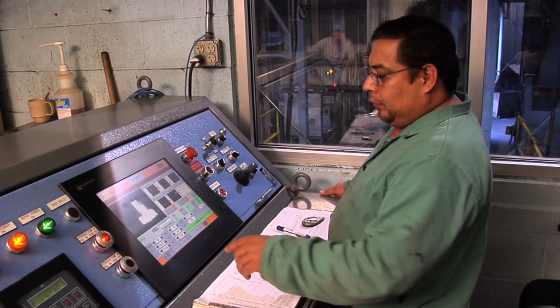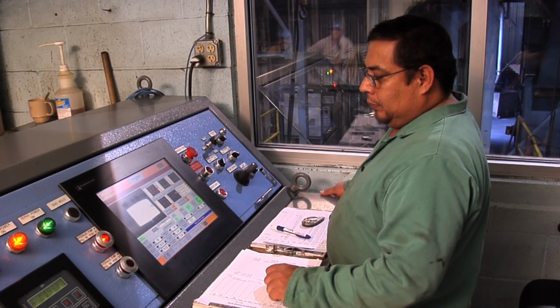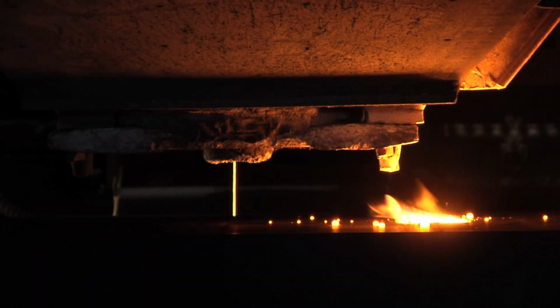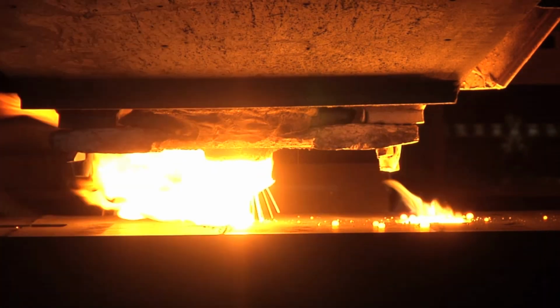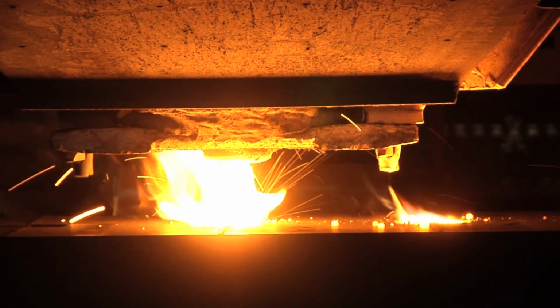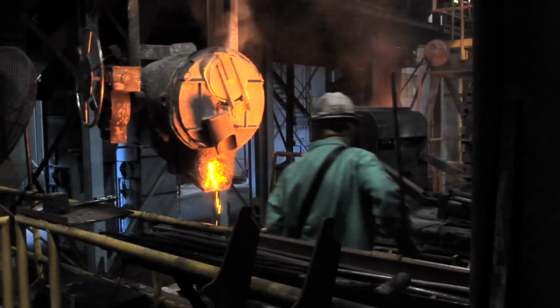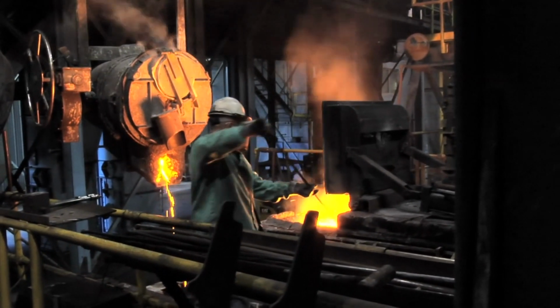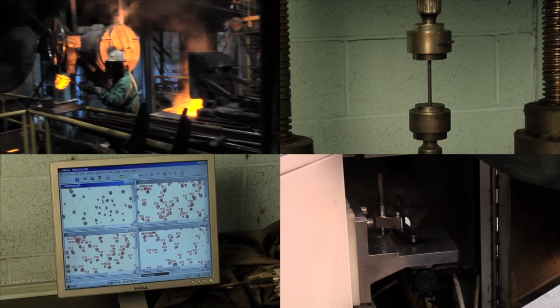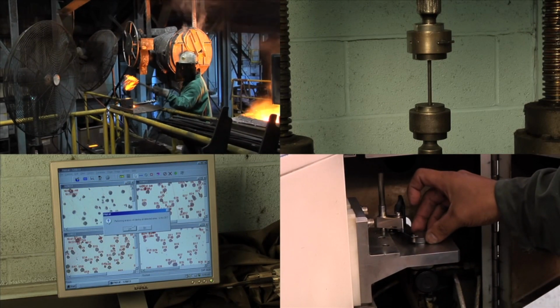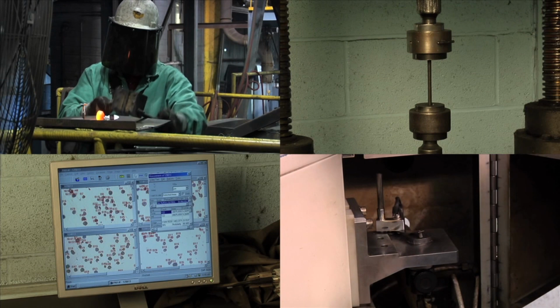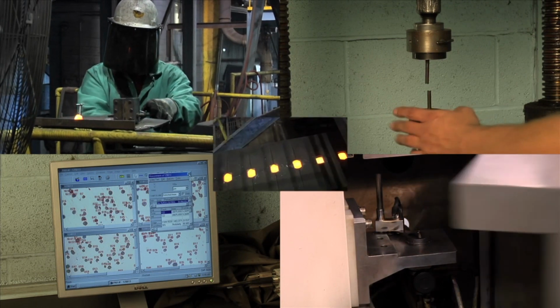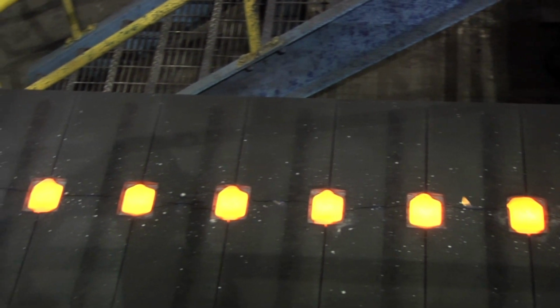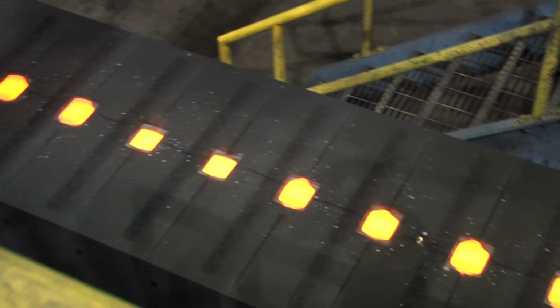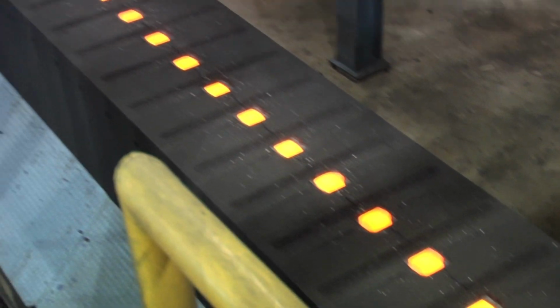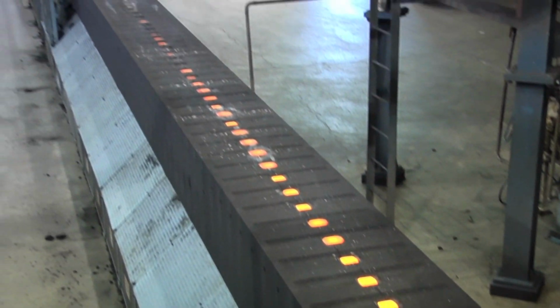Each sand mold block now passes through the pouring machine, where it is automatically filled with a precise amount of liquid ductile iron, heated to temperatures of over 2,600 degrees Fahrenheit. A sample of the treated ductile iron is taken, and its properties are assured. In all, a total of 4 quality assurance checks are eventually performed throughout the process to assure the physical properties of the iron. Once the pouring process is completed, the sand molds continue traveling along the conveyor line, allowing the once molten metal to cool and solidify into a ductile casting.